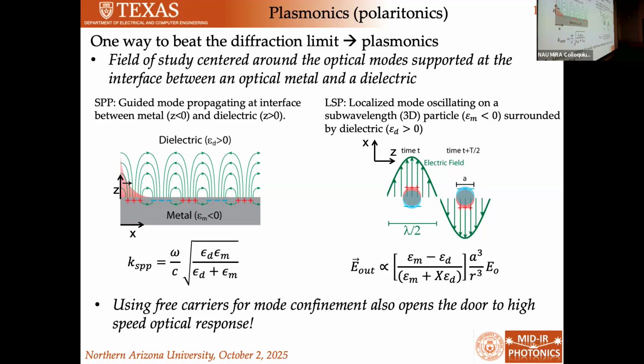And there are different collective excitations that you can couple to, right? There are phonons, the lattice vibrations. There are excitons, these are coupled electron-hole pairs. And there are plasmons. A plasmon is essentially an excitation of charge, so these are charges that are sloshing around. Charge is much heavier than photons. And so this field of plasmonics is the field of optical modes that are supported at the interface between what we call an optical metal and a dielectric.